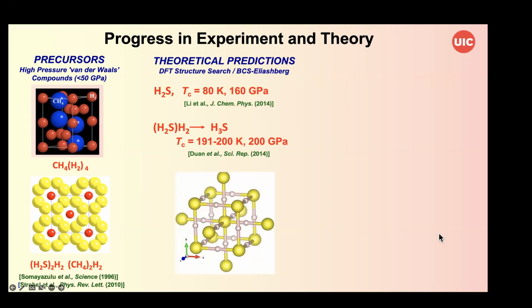Of course, subsequent to this, structure search methods started being applied to these various systems, and in particular to the H2S system, and very important calculations that we're all aware of were conducted that predicted that these could in fact be very interesting atomic-based hydrogen-rich superconductors, in particular this H3S structure that has a Tc of 200 Kelvin.